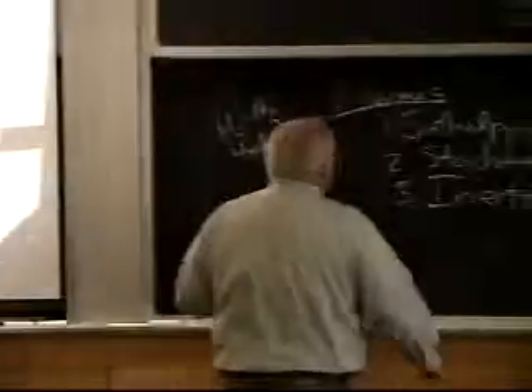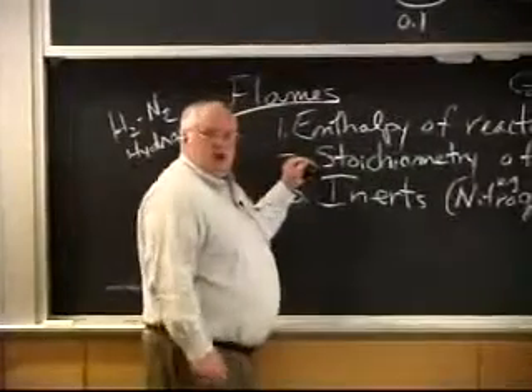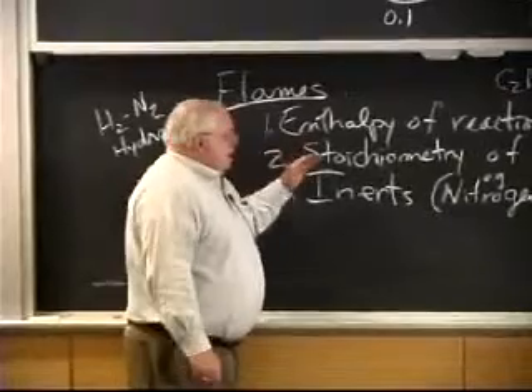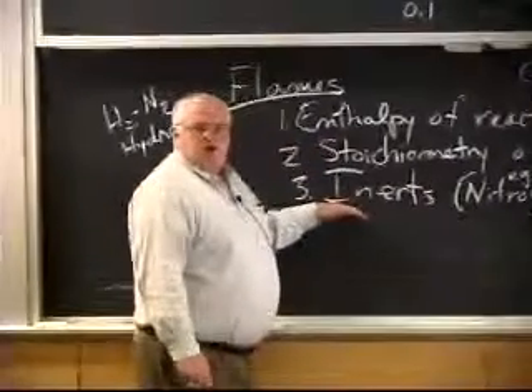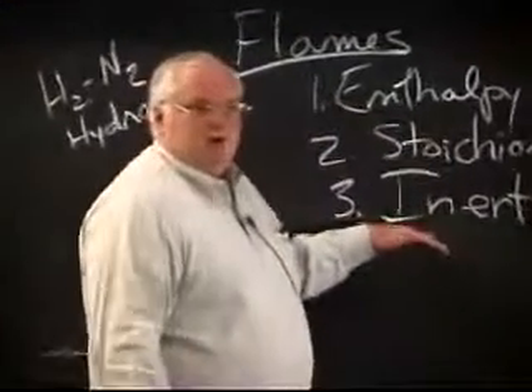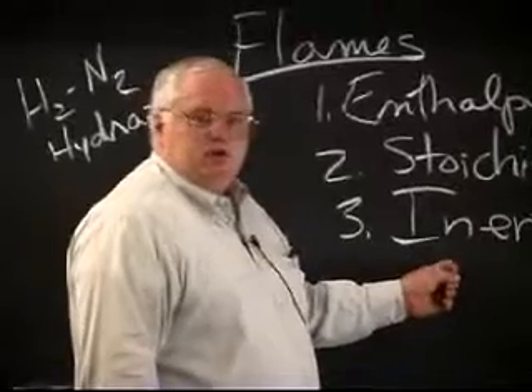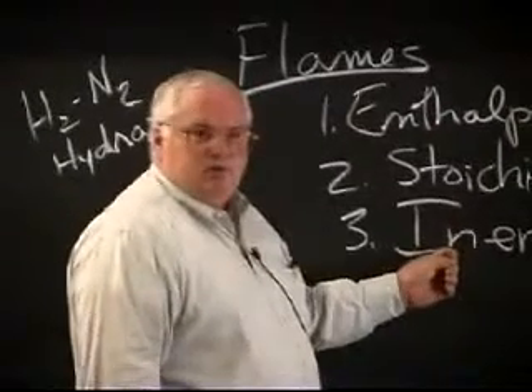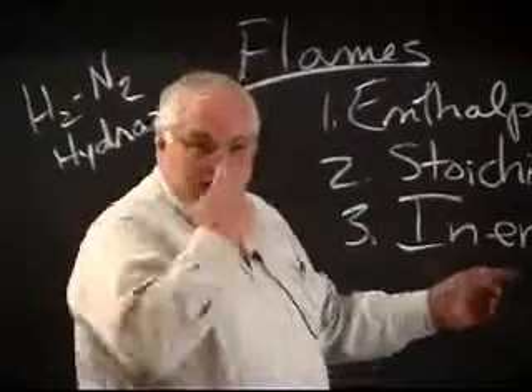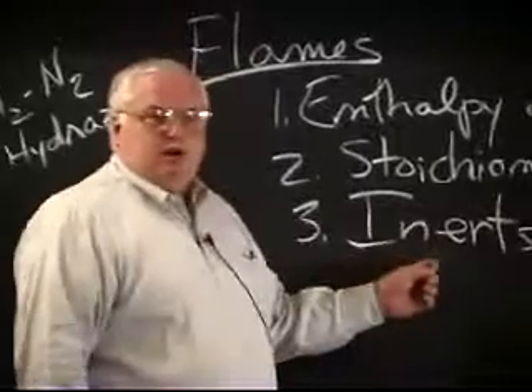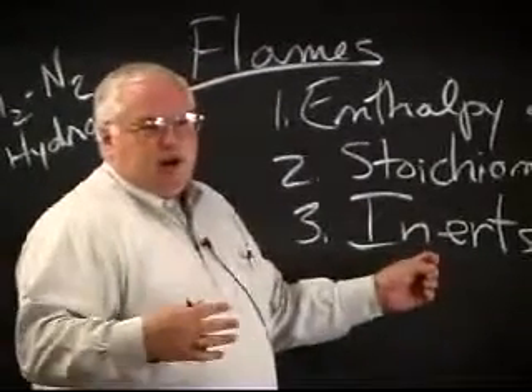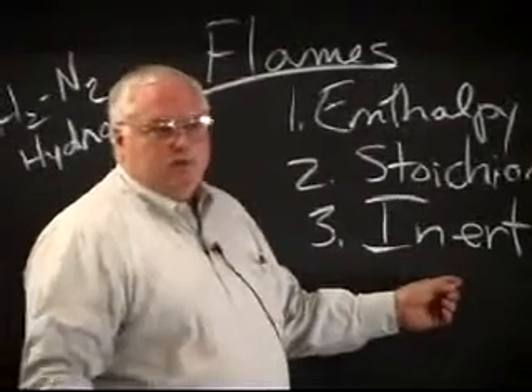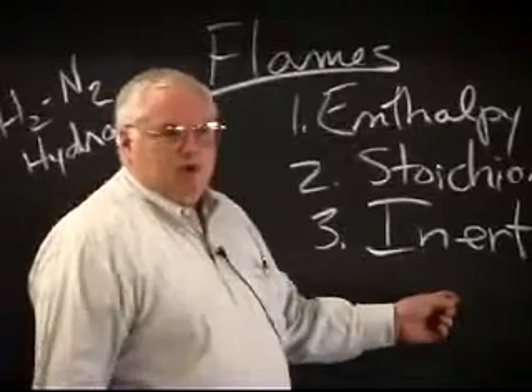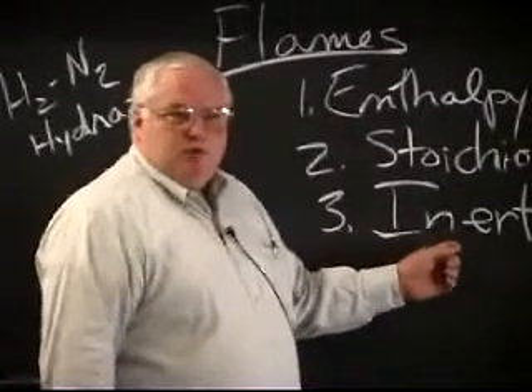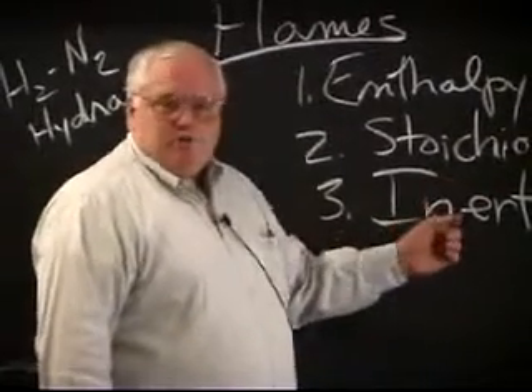To get the highest temperature, you've got to be near stoichiometry. Otherwise, if you're rich, you have a lot of unburned fuel, and it's basically like inerts. The heat of reaction, let's say you've got 20% of your atoms reacting, the other 80% is just baggage that the 20% has to use this enthalpy to heat up. And so it's going to drop the maximum temperature you can get, because you don't have all the atoms participating in the reaction.